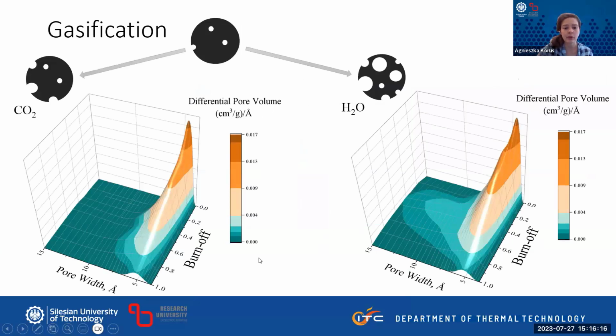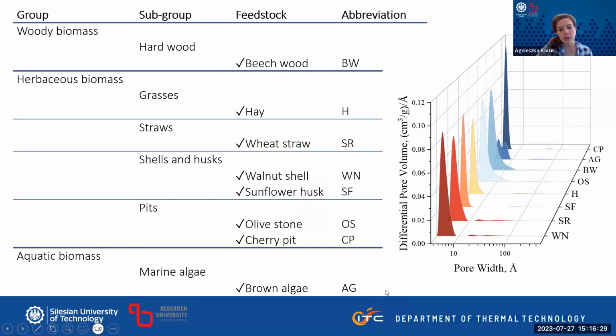We used it previously, for example, for sewage sludge, where we studied the pore development during gasification with CO2 and steam. But for this research, we didn't use sewage sludge. We used chars from agricultural and forest residues. We tried to select a few examples of different biomass groups. Here you can see the pore distribution in the pyrolyzed chars before the gasification. We do the char preparation in two steps. We first pyrolyze them, and then we try the gasification with different parameters. You can see that the olive stones and beechwood, even after pyrolysis, have quite a wide pore distribution.